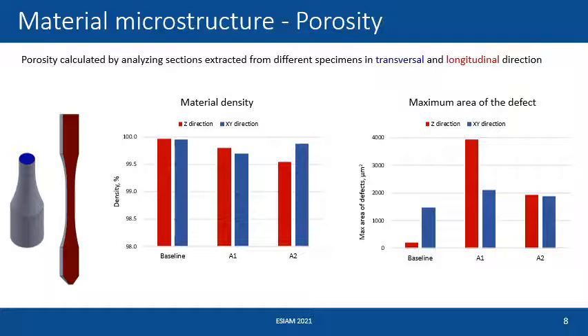in longitudinal direction. A similar trend is visible also if we consider the maximum area of the defect that we can find in both the two sections. Even if we can see that the A1 process parameter set still has a higher density, it tends to introduce some bigger defects compared to the A2 set. The A2 set produces a wider diffuse porosity, but with small pores compared to the A1 set.